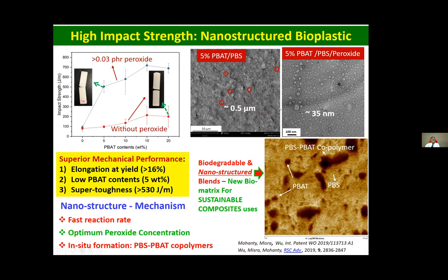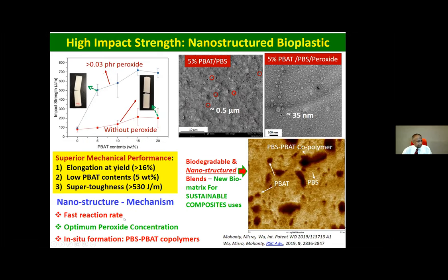So elongation of the plastic increased by 16 times. Low PBAT content, only 5%, unlike 50% or 60%. A super tough polymer we could make. Impact strength is quite high. So fast reaction rate, optimum peroxide concentration, in situ formation of polybutylene succinate and polybutylene adipate terephthalate copolymer.